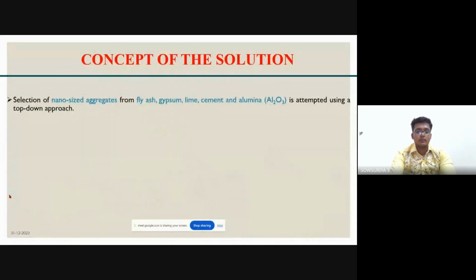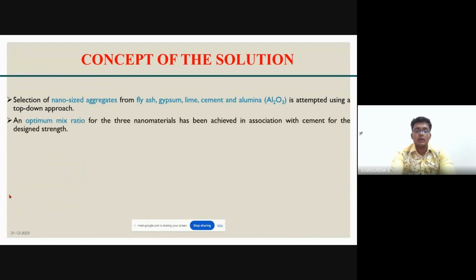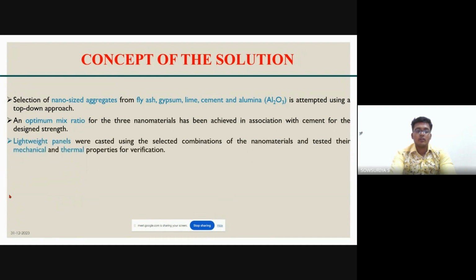This is the concept of the solution. Selection of nano-sized aggregates, which includes fly ash, gypsum, lime, cement, and alumina, is attempted using a top-down approach. An optimum mix ratio for these materials has been achieved in association with cement for design strength. And these lightweight blocks were casted using a selected combination of nanomaterials and also tested for both mechanical and thermal properties for verification. And the prepared blocks are very lightweight, strong, and durable based on the test results.